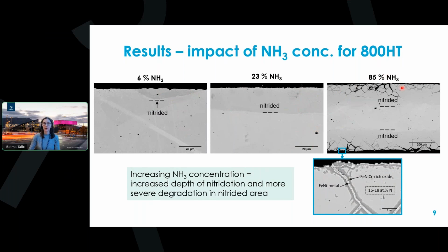For 800 HT, we can see that at the highest concentration of ammonia, the nitrided zone has extended almost 200 micrometers beneath the surface of the component. And we also have started to have phase separation in the nitrided area if we zoom into the lower part here. And we also see intergranular cracking of the nitrided zone.